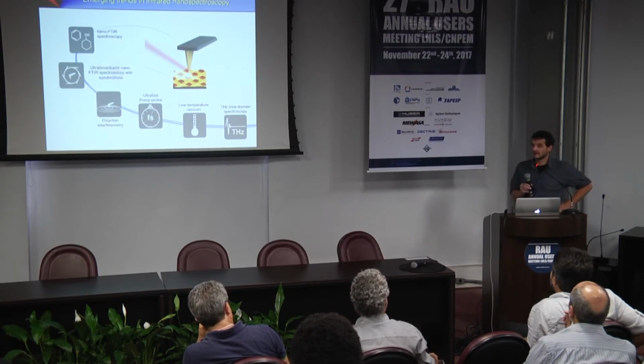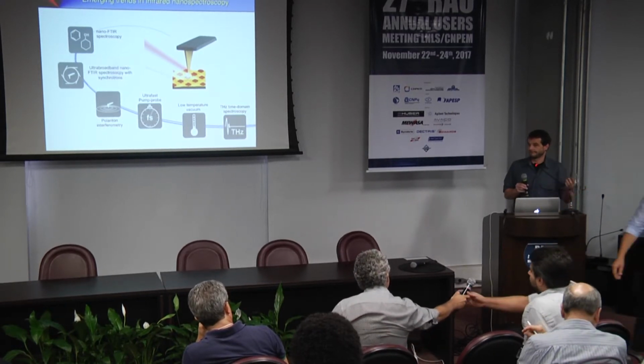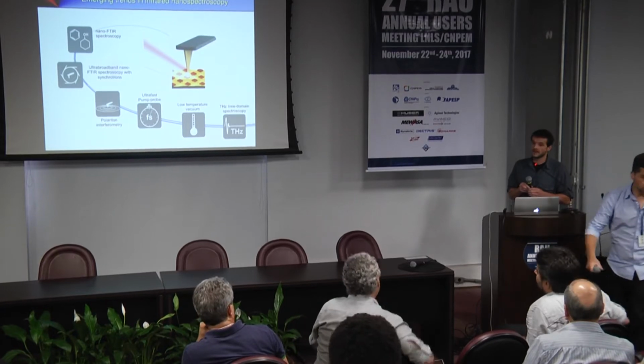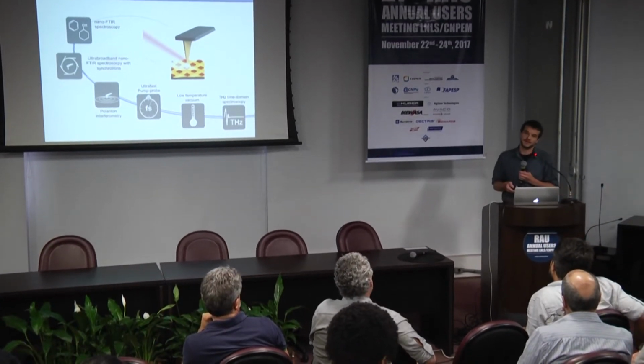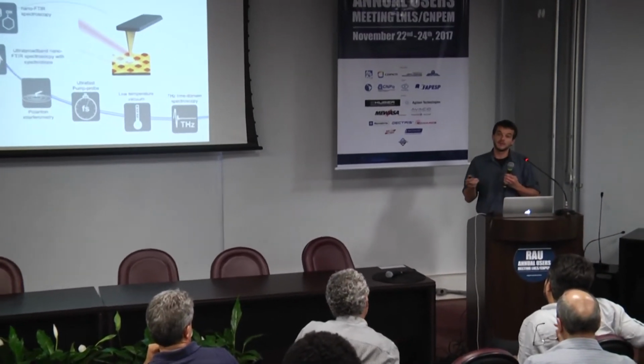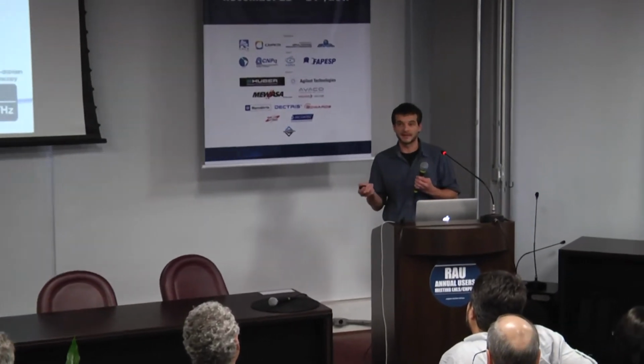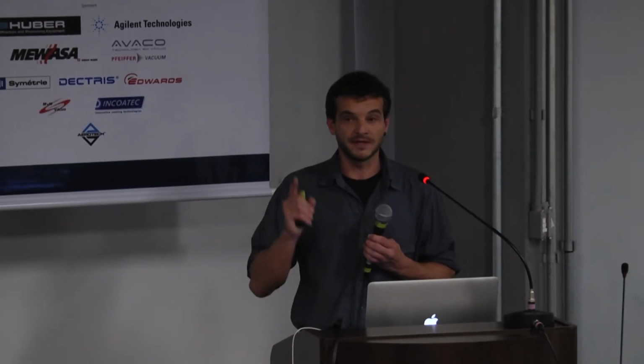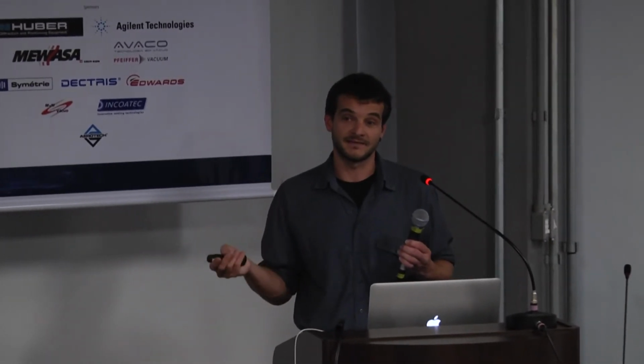We call it scattering type near-field optical microscopy, but in the end, I think a better word would be tip-enhanced infrared microscopy, because we use metal tips, and these metal tips make a field enhancement, and it's exactly the same as people do in tip-enhanced Raman spectroscopy. The difference is we do elastic light scattering, and in tip-enhanced Raman, you need one visible laser, and you get the whole spectrum at once, and this is inelastic scattering.